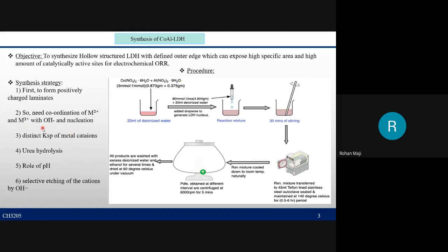For that, we consider the distinct Ksp of them, because Ksp represents the maximum extent that a solid dissolves in solution. So, by different dissolution, the LDH laminates would presumably form a core-shell structure under the condition of urea hydrolysis. Now, why choose urea hydrolysis? Because there is a crucial role of pH. As we have seen in the gibbsite experiment also, urea hydrolysis makes the solution alkaline, which helps in the selective etching of the cations by OH-, thus avoiding a second modification step.